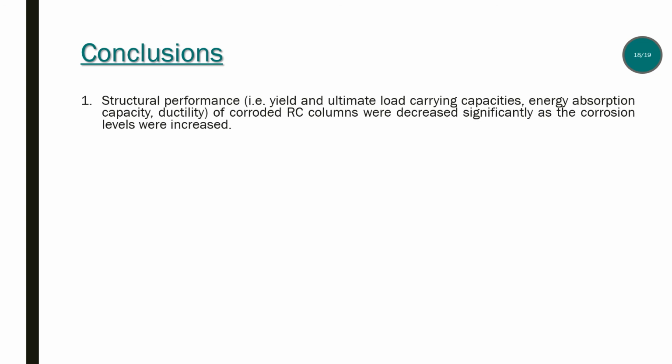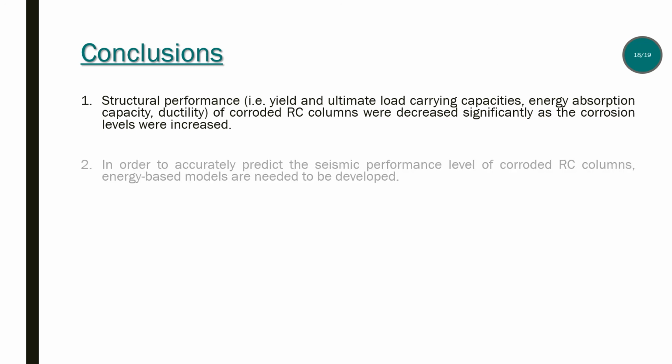The conclusions of this study can be summarized as follows. Structural performance of corroded reinforced concrete columns decreased significantly as the corrosion levels increased. In order to accurately predict the seismic performance level of corroded reinforced concrete columns, energy-based models need to be developed.